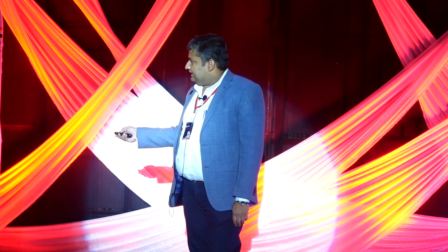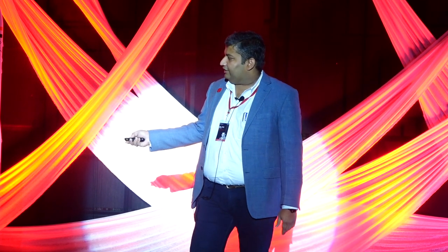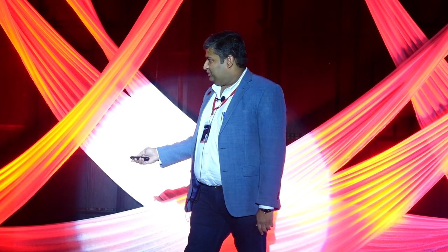So then on the right hand side, you see a scanning electron microscope image where the thinned regions were clearly evident. We tried to charge it inside the electron microscope and discharge it and see how the fluoride ions were moving throughout at the cathode electrolyte interface. And what happens also is some defects are formed, which are few nanometers in length. And there was also some amorphous carbon, and crystalline carbon was formed during the whole process. And it was a study of its own. It was the PhD thesis of Mr. Mohammed, or Dr. Mohammed now.